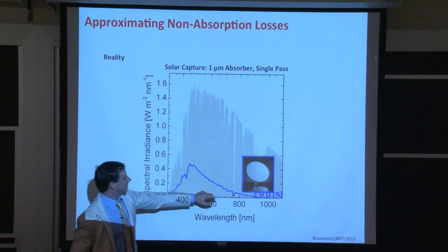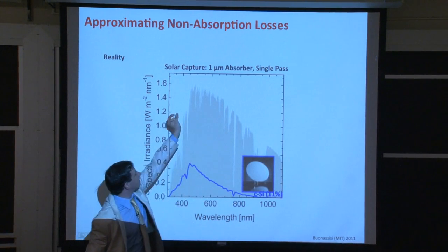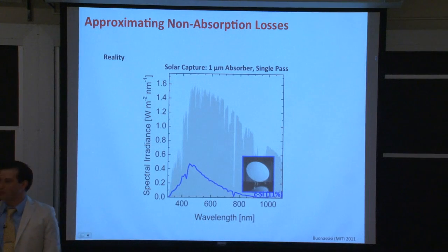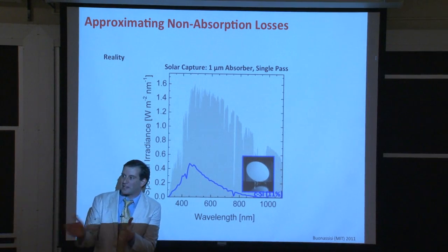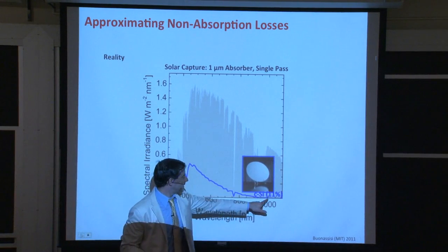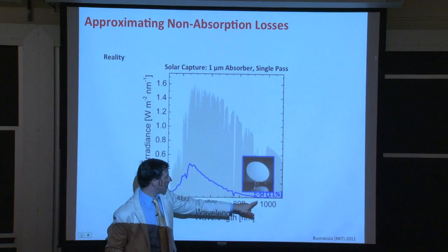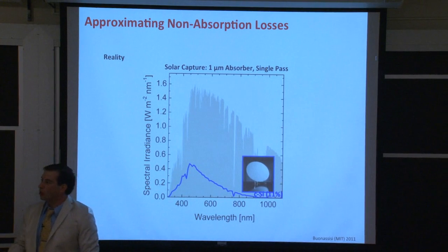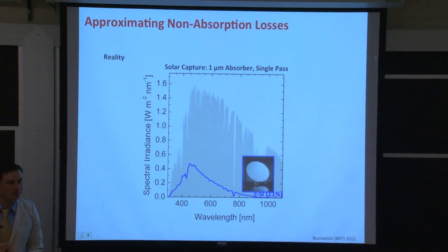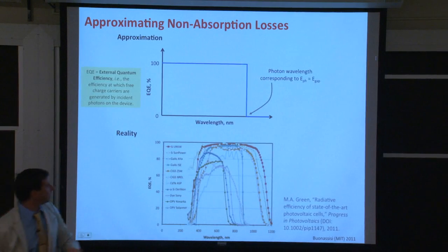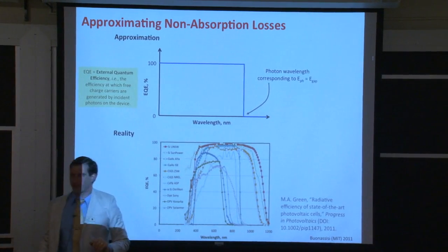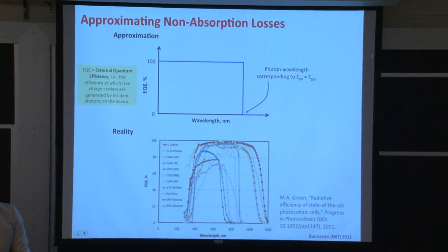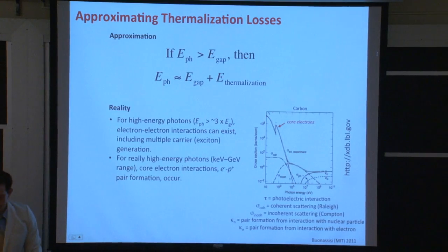Right? So instead of just a sharp turn-on, if you had a 1 micron thick silicon wafer, and we calculated last class that we needed somewhere around 10 microns or 100 microns to absorb light well, if we reduce the thickness of the wafer to 1/10 or 1/100th of what's necessary to absorb light well, we don't see that sharp turn-on at the bandgap. We see rather a gradual turn-on of our silicon as we move to shorter and shorter wavelengths that are absorbed more and more efficiently by the device. So again, we're just wrapping our head around the basic concept that we're going to use for the purposes of our calculation, but again, some of the more fine structure, some of the more advanced concepts come into play when we're doing more detailed calculations.